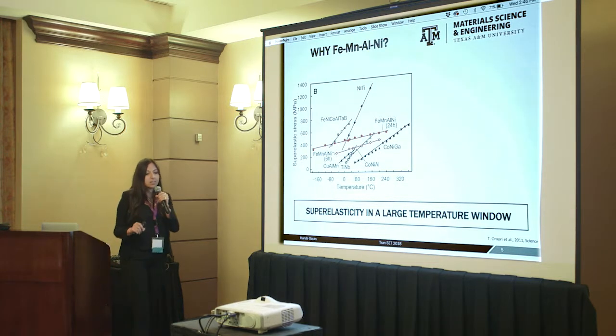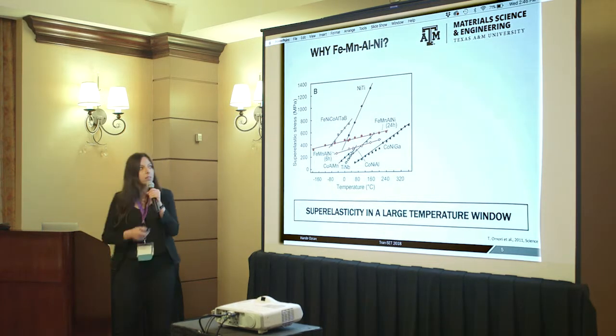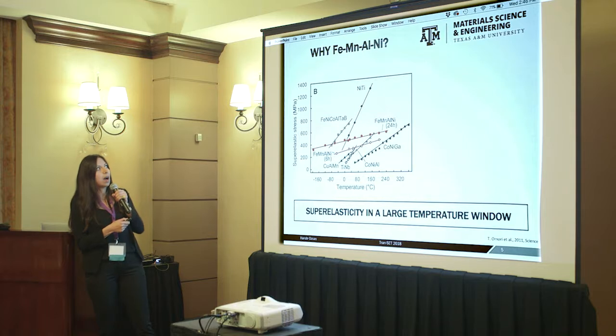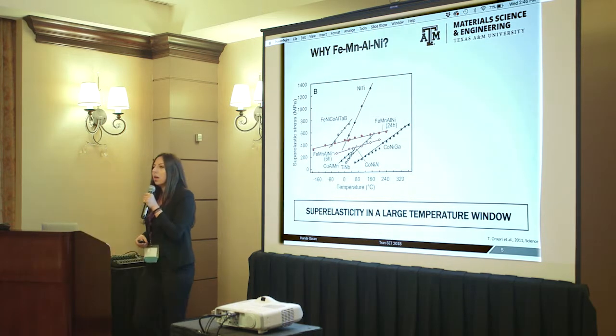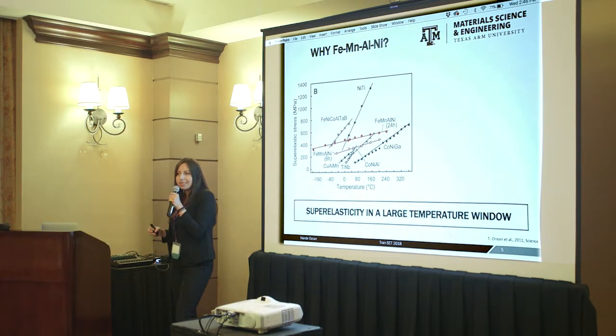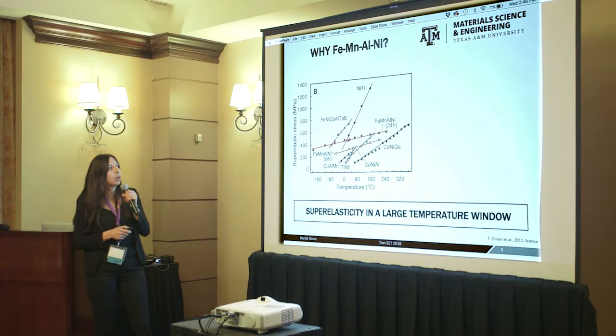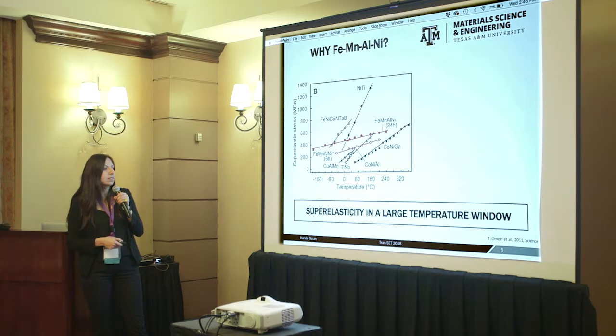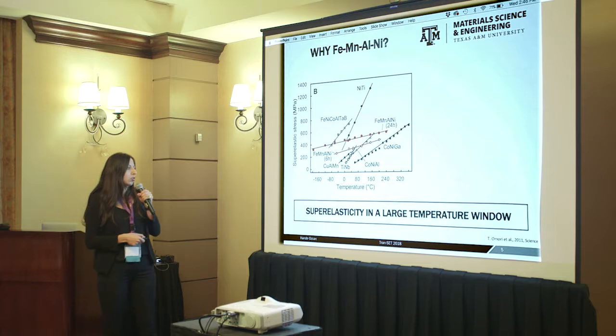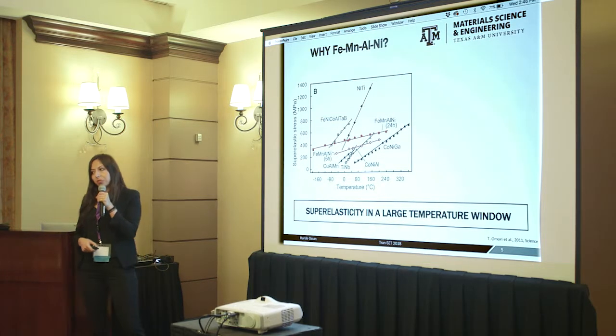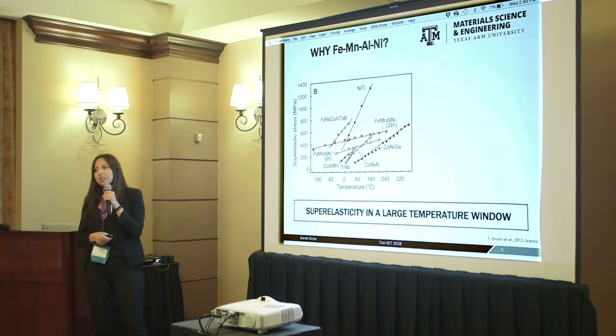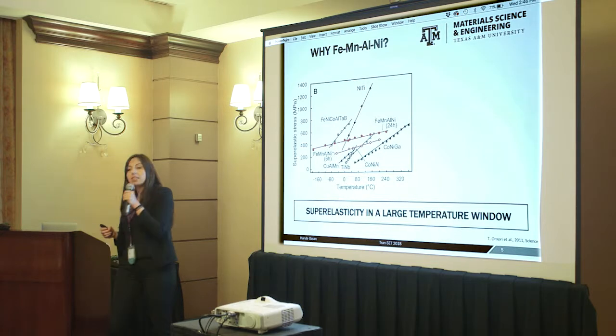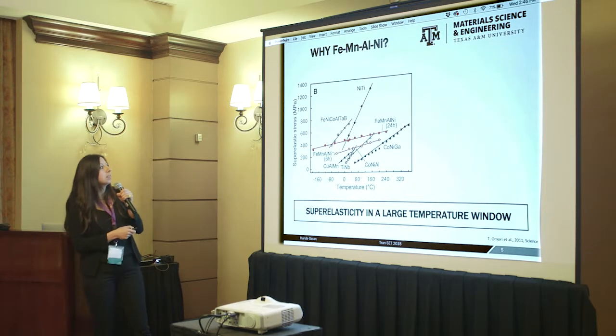So in our study, we chose a class of iron-based shape memory alloy called iron manganese aluminum nickel. What's so special about this iron-based alloy is that it shows superelasticity in a large temperature window, and the properties of the material are not dependent on the temperature.